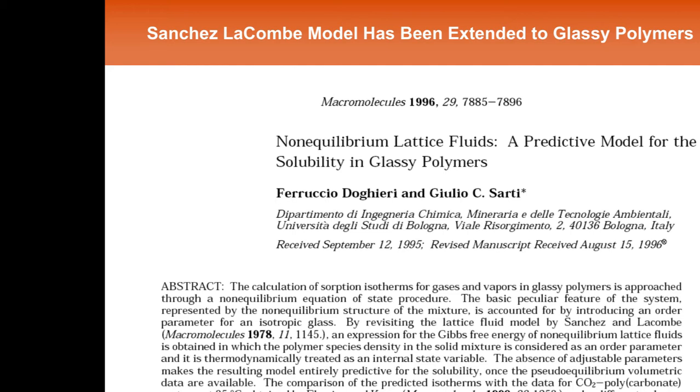And the NELF model can describe these data. The curves and the dashed line are the NELF model predictions, knowing only the density of these samples at the penetrant-free condition. So once you've taken this sample back down here, take it out, measure the density, and with that information, you can predict the sorption, and likewise. So this gives the first ability to actually predict these sorts of hysteresis or conditioning effects in gas sorption or penetrant sorption in polymers.